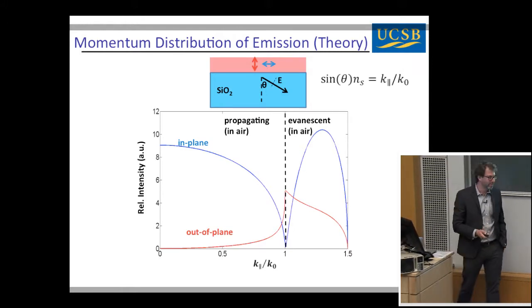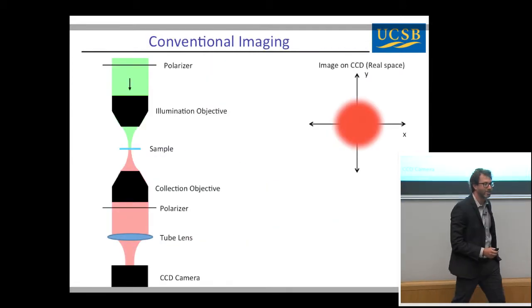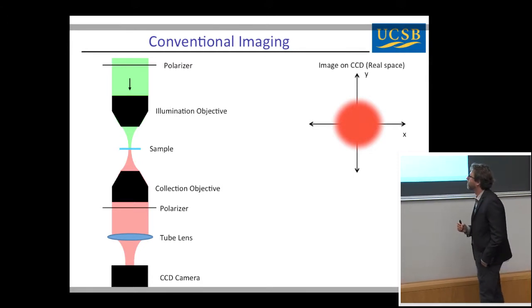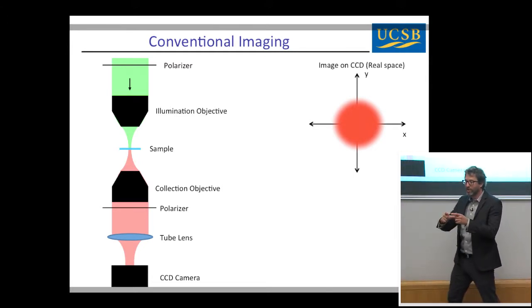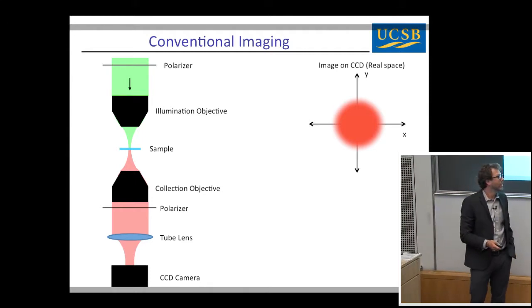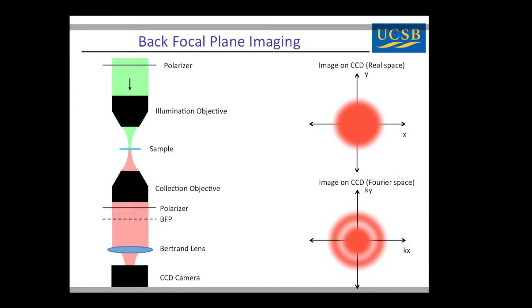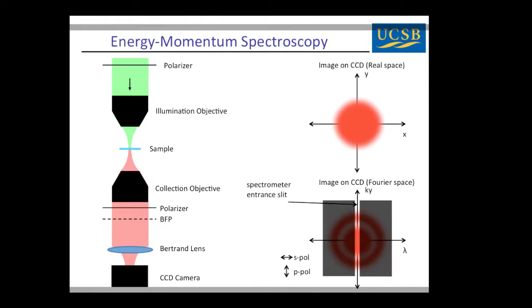So how do we do that? This was done in collaboration with Rashid Zia at Brown, where instead of doing conventional imaging, right, so in conventional PL imaging, every point on my CCD chip corresponds to a distinct position on the sample. So what Rashid developed was a Fourier imaging technique. Okay, it's very easy to do, where now every point on your CCD chip corresponds not to a position on the sample, but to a distinct angle of emission coming from the sample. Okay? And for these two-dimensionally symmetric layered materials, we actually don't need this two-dimensional angle information, so we can project that image onto the entrance slit of a monochromator and separate the light by angle in one direction and wavelength along the other axis of our CCD. Okay? So what do we get?